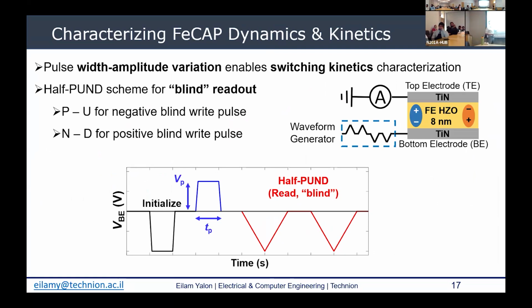It's challenging to get polarization current within that measurement, but what we can do is, following this pulse, we apply two consecutive triangular pulses in the opposite direction, and that will give us the amount of polarization that switched in this pulse. So we call this a blind readout, because we don't read the current here, but we get information about the amount of polarization that switched within this pulse. And now we can vary the pulse width and voltage amplitude separately, and that gives us the full